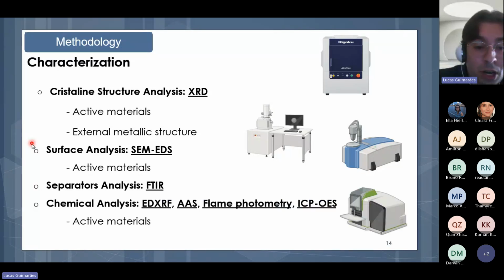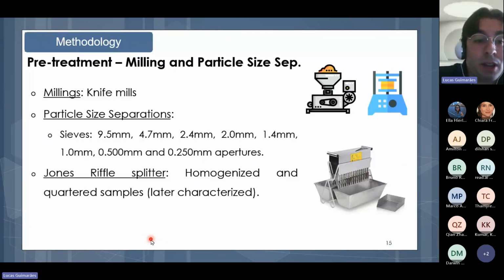And then the active materials were analyzed chemically with X-ray fluorescence, atomic absorption, flame photometry, and ICP OES. The pretreatments, as I said, were millings. Using milling, we performed millings. We used knife mills and particle size separations using different sieves. And at the end, a Jones riffle splitter was responsible for homogenizing and quartering the samples, the final samples that were again characterized.